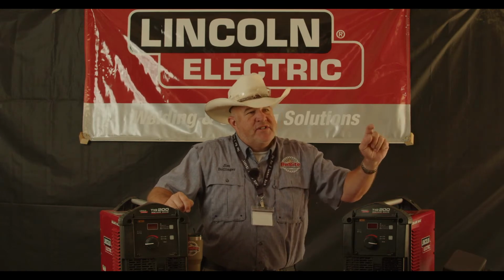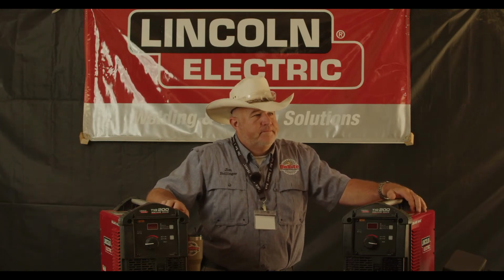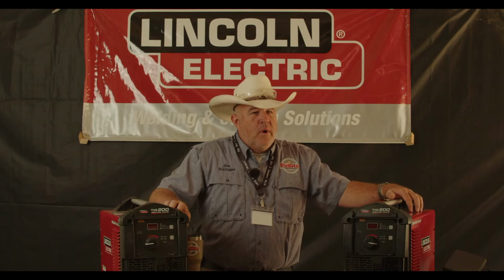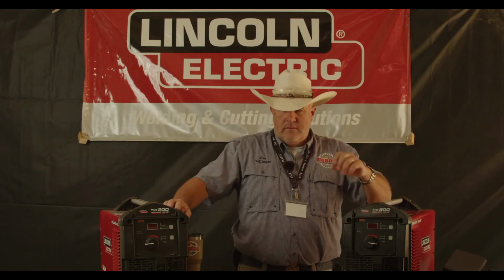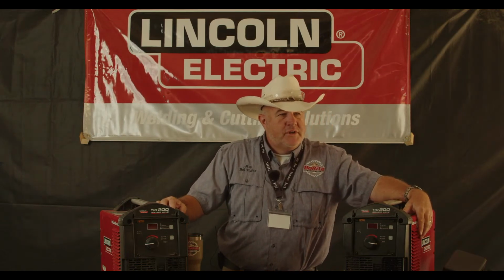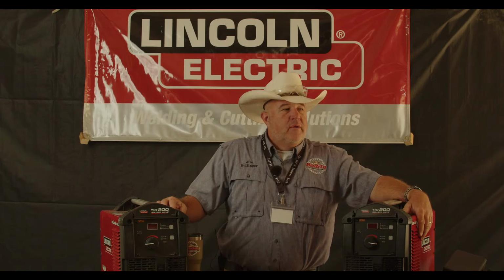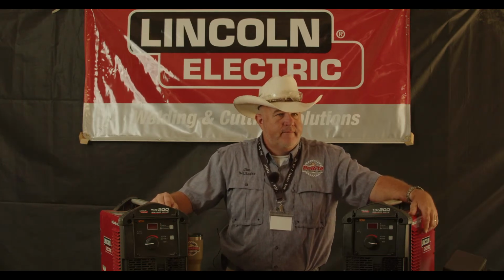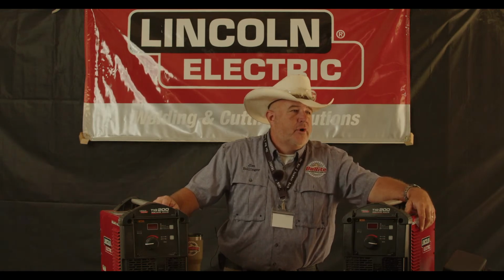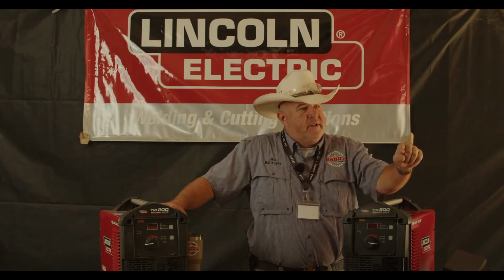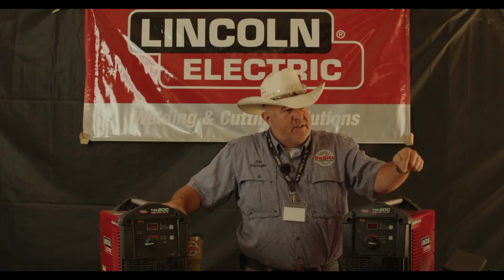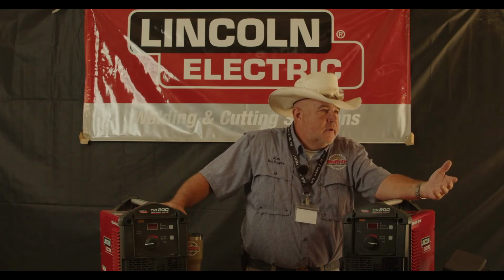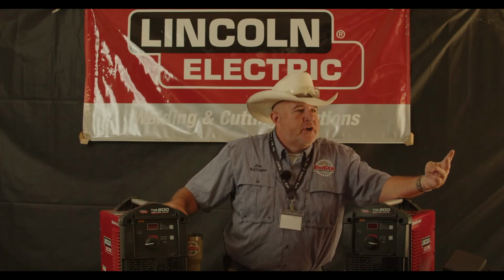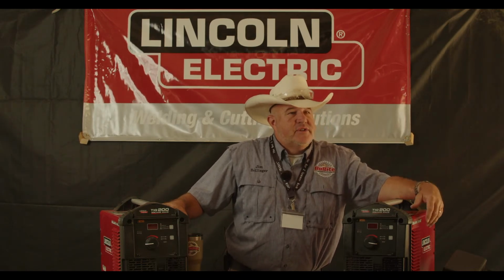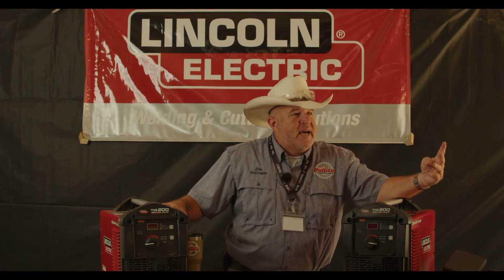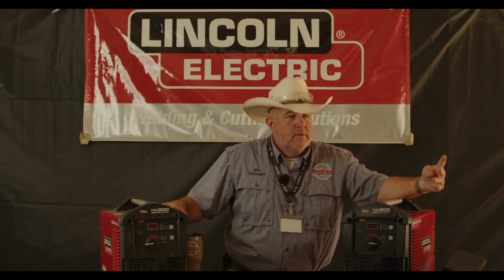Okay? That's the reason we never TIG weld in DC electrode positive. That is the reason we never TIG weld in DC electrode positive. Any questions about that? We TIG weld in DC electrode negative because the inverse of what we talked about now becomes true. 3,000 degrees of heat is in the tungsten. 7,000 degrees of heat is in the plate. How hot is the tungsten now? 3,000 degrees. What temperature did I tell you it melted at? 6,280 degrees. So that tungsten can take that 3,000 degree temperature range, right? Does that make sense?